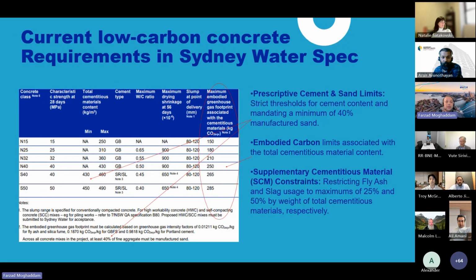Moving to Sydney Water, in our current spec we still have some prescriptive requirements, as you can see, maximum and minimum, including a maximum water to cement ratio. But we also added a couple of years ago, I think, a maximum embodied carbon column for cementitious material. So we're pushing a little bit, pushing suppliers to come up with more low carbon concrete. We also require at least 40% manufactured sand. And at the moment in our spec, suppliers can only use up to 25% fly ash or 50% slag.